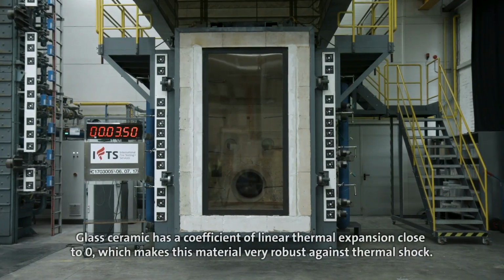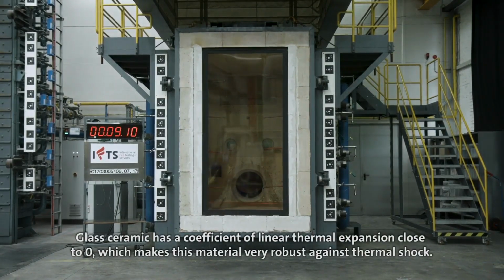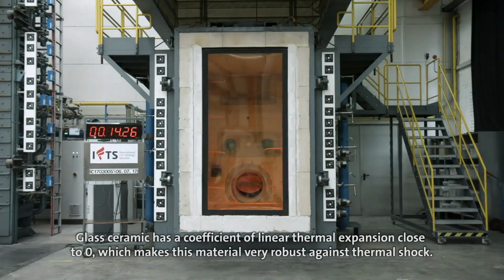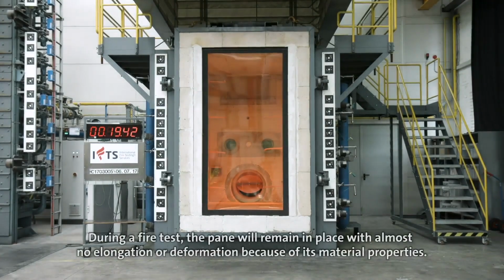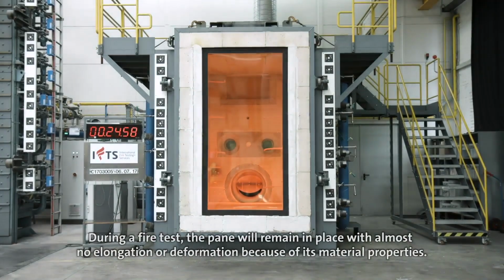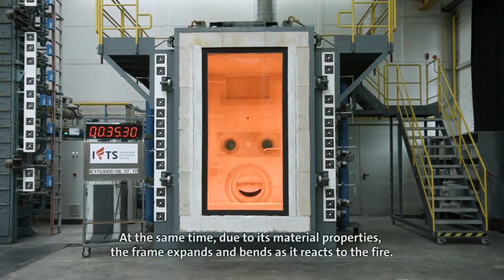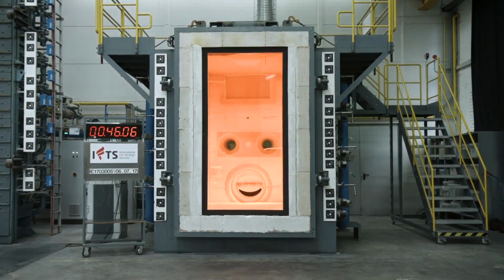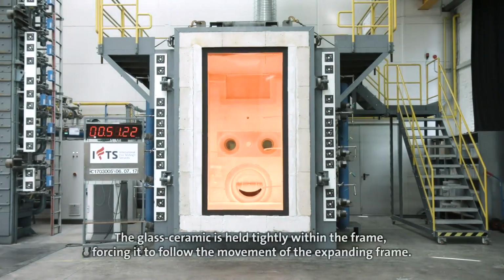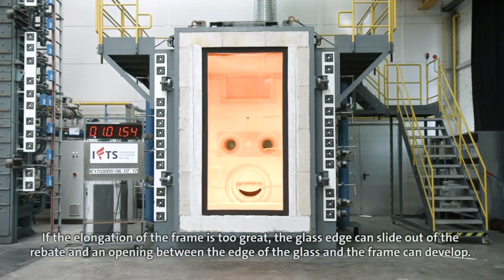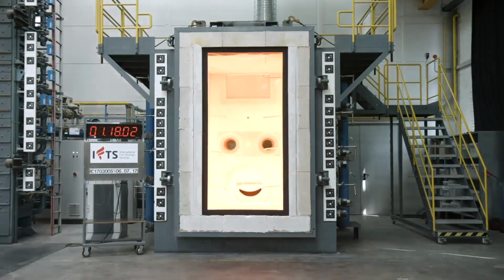Glass ceramic has a coefficient of linear thermal expansion close to 0, which makes this material very robust against thermal shock. During a fire test, the pane will remain in place with almost no elongation or deformation because of its material properties. At the same time, due to its material properties, the frame expands and bends as it reacts to the fire. The glass ceramic is held tightly within the frame, forcing it to follow the movement of the expanding frame. If the elongation of the frame is too great, the glass edge can slide out of the rebate and an opening between the edge of the glass and the frame can develop.